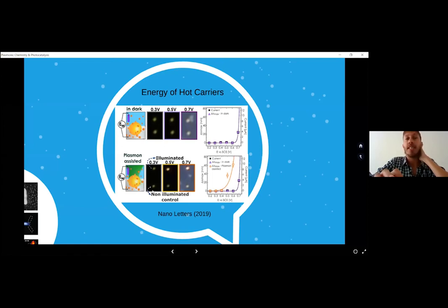And we could see that for the illuminated nanoparticle, that happens at lower voltage, right? So there is a photoelectrocatalytic effect. The reaction is happening at a lower voltage, and this is due to the energy that the hot electrons are able to supply to the reaction in order to perform it at a lower voltage.